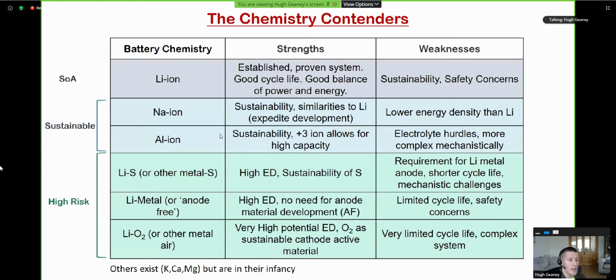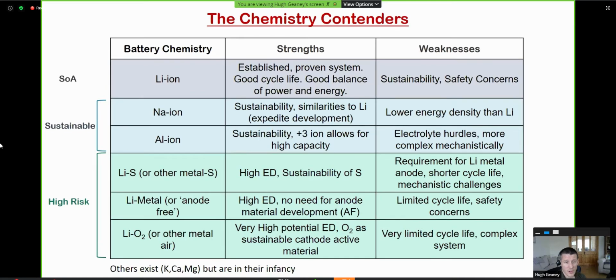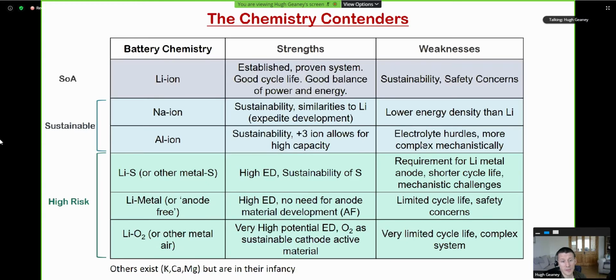But fundamentally, it seems that the energy density is always going to be lower in sodium-ion than it is in lithium-ion. On the aluminium-ion side, this is probably slightly further behind in terms of development. Sustainability is even more of a bonus here compared to lithium and sodium. And there's also potential for the +3 ion that could allow for higher capacity of the material in the first case. At the minute, it's kind of hung up on the electrolyte. Electrolyte stability is a big issue, and the electrolyte choices are drastically reduced compared to lithium and sodium. As a result, linked to that, the actual mechanism for the battery is more complex as well.